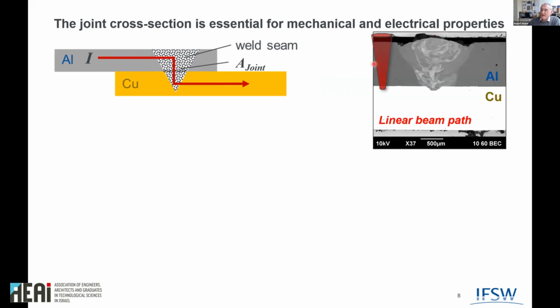And if we have now this straight moving beam shown here as a sketch, this is what we end up with, such a weld. So this is a cross section, the same as here, this grinded, that you can see what is going on. The darker material here is the aluminum, on the bottom the brighter is copper. And this, what you can see here, is the laser weld which was done. This was already a very nice and very good weld. You can see that only a little copper is molten, which is important to have a good conductivity. But what you also can see is that the cross section is quite small, and also that the copper is distributed all over the weld.